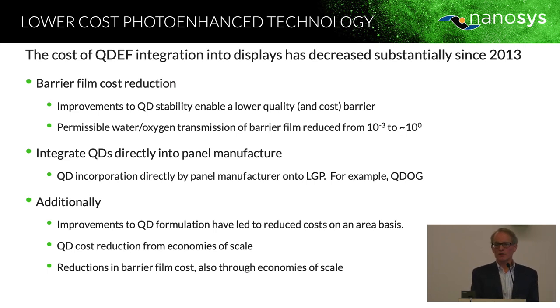Well, what has to happen in this market? I showed you earlier that quantum dot technology is really leading the high-end display market, but it's also important that we push that down into the mass market. It's important for us to gain volume, and that's happening. In fact, I can tell you that the selling price for quantum dots, or quantum dot enhancement film, has declined 30% year over year since 2013. And so how does that happen? Well, we weren't making it very efficiently back in 2013, but there are a number of things. One is barrier film cost reduction. We've learned how to make the quantum dots much more stable over time, and so we've decreased the requirements of this barrier, which used to have to be an ultra barrier to keep out oxygen and moisture, by two or three orders of magnitude. And I can tell you this requirement is very close to going away completely, in which case barrier film will no longer be needed. Additionally, there are ways to integrate the quantum dots directly into the display without a separate film manufacturing step, for instance, quantum dot on glass, which I just talked about.